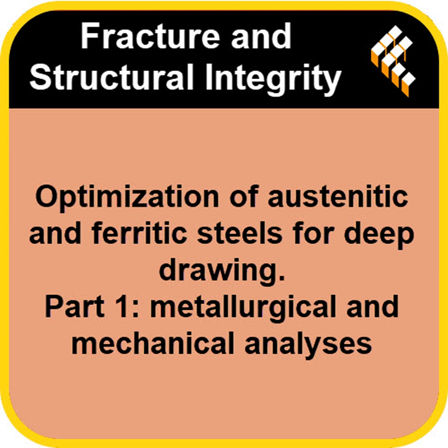Clever. Okay, so lubrication is king. What about the other factors? Blank holder pressure and punch speed. They mattered, but less so. They were statistically significant, yeah. But their effect was much smaller than lubrication. For blank holder pressure, maybe slightly counterintuitively, a lower pressure was actually better. Lower pressure helped. Why? Lower pressure, the 6.6 MPa level they tested, just makes it easier for the sheet metal to slide inwards from the flange area. It allows more material to feed into the die, reducing the stretching demand on the material already over the punch. High pressure, 59.2 MPa, restricts that flow more.